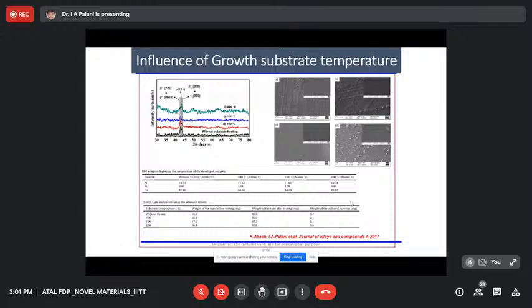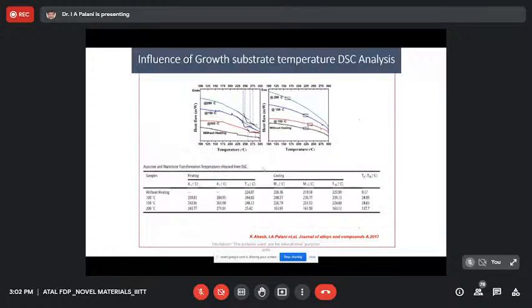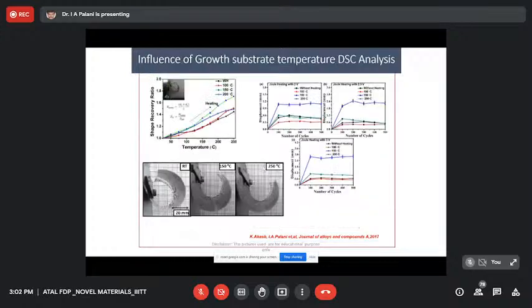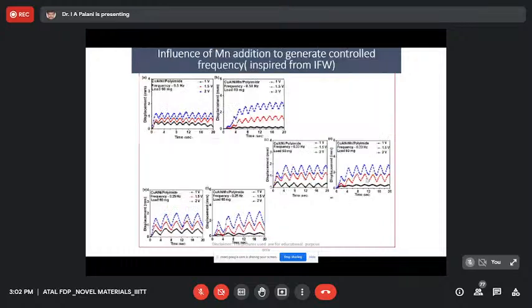For that, we want to do some kind of structure growth, that is, we want to change the overall behavior of it. We want to investigate the influence of substrate temperature, that is growth temperature, on the development of the bimorph. So we went for 100-degree deposition, 150-degree deposition, and 200-degree deposition. The phase transformation was almost the same, but when we looked into the recovery part, the samples at 150 degrees Celsius showed a better displacement compared to the others. That's how we narrowed it down, and this is how we studied the life cycle behavior of it.